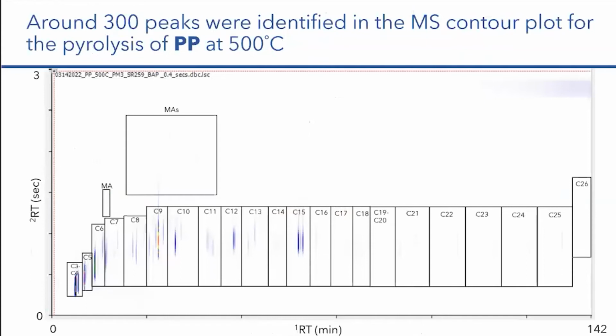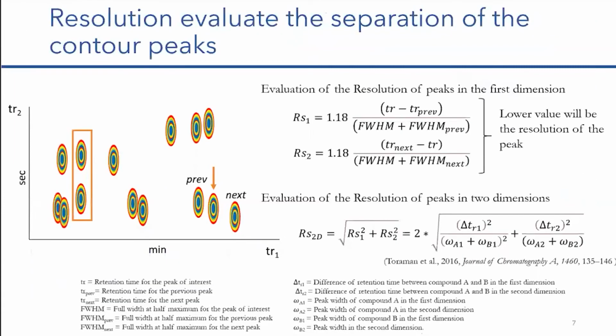This is an example of the chromatogram that we obtained for the pyrolysis of PP at 500 Celsius. We were able to identify around 300 peaks here, and we went from C3 to C26. In addition, we identified some monoaromatics. So the resolution in this case is one of the factors to analyze to see that the chromatogram is in good shape.